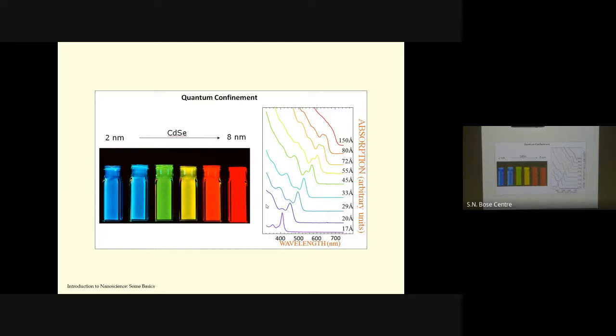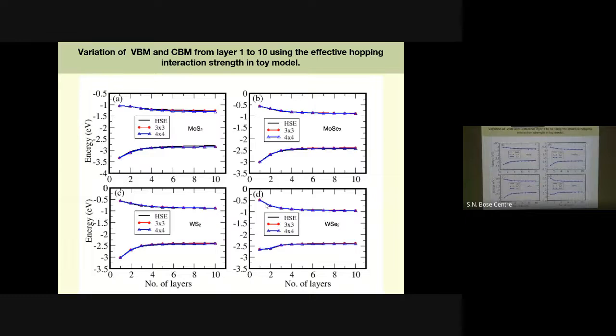And so in these covalent materials, you have a size dependence of the band gap. Whereas when you come to these materials, which are van der Waals stacked, you are talking about a similar size regime, but you don't see any size dependence in these cases. And almost beyond, say, 3 or 4 monolayers, your size dependence is almost invariant, and it's similar across the entire series of materials.